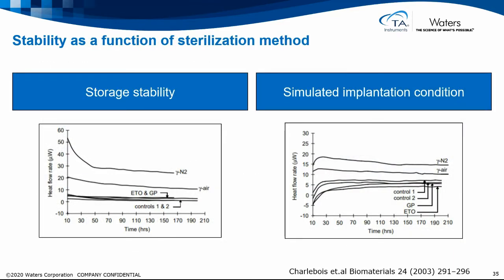We see here stability testing as a function of storage stability. In the first one, we have different sterilization methods. The control that's unsterilized and ethylene oxide or gas plasma sterilization yield almost no reaction at all, but samples that have been gamma irradiated, both in nitrogen and air, show much higher reaction rate in the microcalorimetry. Now you can see that this is measured for a very long time. Typically you do not need to measure for this long period of time, but to learn about the material, sometimes they are measured for long periods of time.